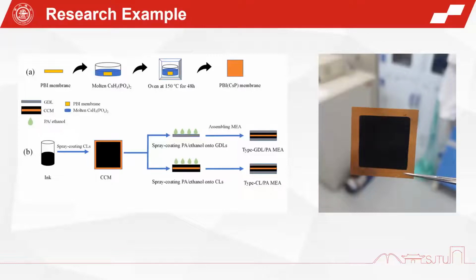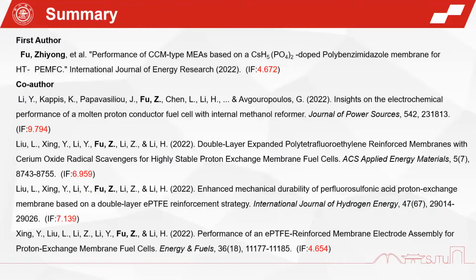On the right, it can be seen that the surface of the cesium pentahydrogen phosphate doped PBI membrane remained clean and flat without any distortion after spraying the catalyst layer, and no visible cracks appear in the catalyst layer. So, based on that, I have published a paper as first author. It is named Performance of CCM type MEAs based on a cesium pentahydrogen phosphate doped polybenzimidazole membrane for high temperature PEMFC in the International Journal of Energy Research, and four other papers as co-author.